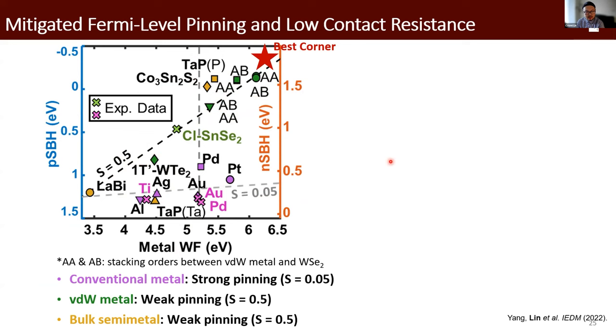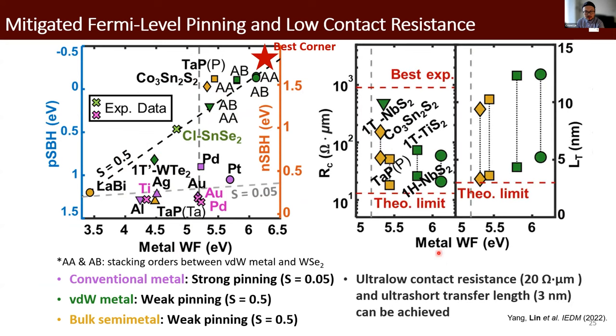And with a multi-scale simulation approach, we also estimated the contact resistance, and these material candidates show contact resistance of below 100 ohm micrometer, and they can even go down to 20 ohm micrometer. And there's also some benefit about the scaling as characterized by the transfer length.